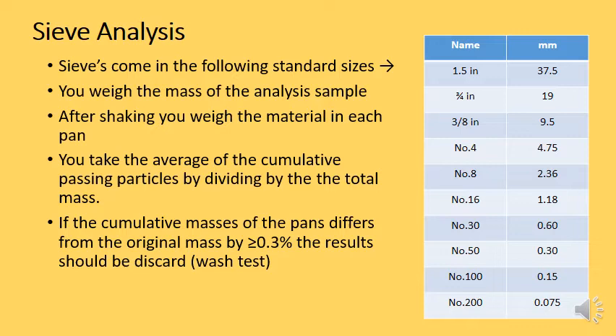Now, if you take all of the sieves together and you take all of the cumulative masses, and that is different from the original mass by more than 0.3%, that means you've lost some of the aggregate, or some aggregate fell in. This is called a wash test. It's a way to ensure that the sieve test you're doing is accurate, that it hasn't been corrupted by some of the mass of the aggregate being lost and falling out of the experiment. So if it's greater than 0.3%, the wash test, it means you need to do the sieve test again.